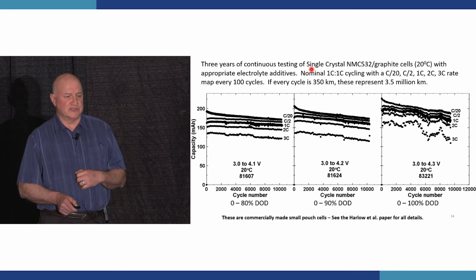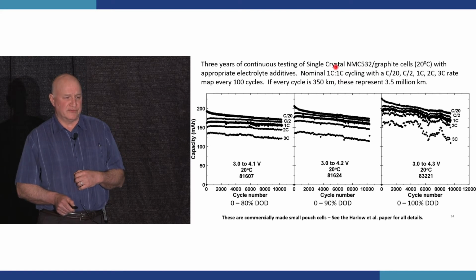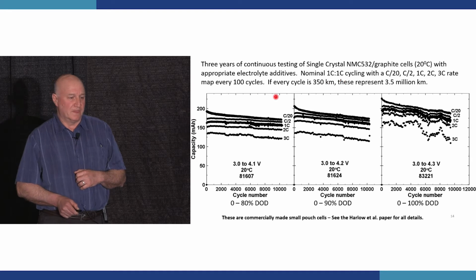They use a so-called single crystal NMC 532 positive electrode material with graphite negative. They're operating here at room temperature. They're doing a 1-hour discharge and a 1-hour charge. And they have what we call a rate map every 100 cycles. We'll start with this panel over here on the left side.